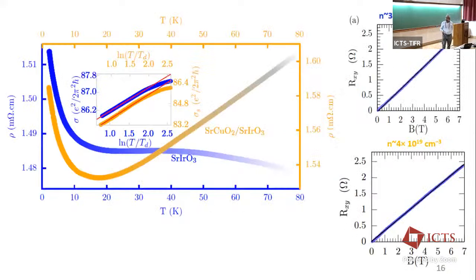Now we look at the resistivity plot. This is for the bilayer, and this is for the bare SrIrO3. There is an upturn, and this upturn follows a logarithmic temperature dependence, which could be due to weak antilocalization. There could be some correlation. And the carrier concentration for both layers comes around 10 to the power 19, which is what we expect because it is a semi-metal.